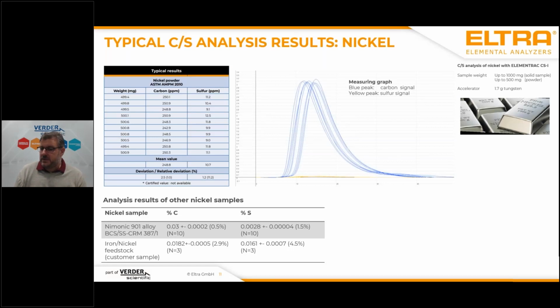And here you see what we get. We had a nickel alloy, which is the standard, where we get concentrations of about 0.03% of carbon. And then we also have this iron nickel feedstock, where we also get an analysis of 0.0182% of carbon. These are typical results for these samples, but nevertheless, you can also get reliable results for higher and lower concentrations.